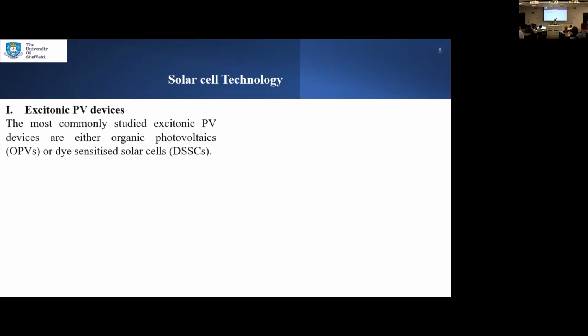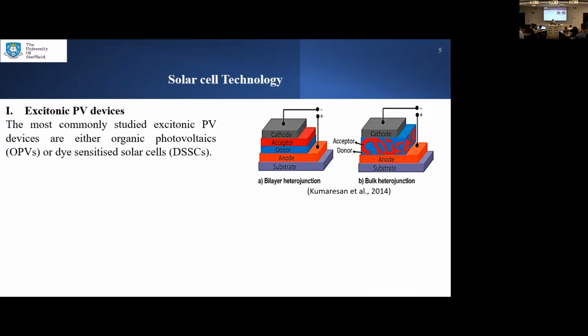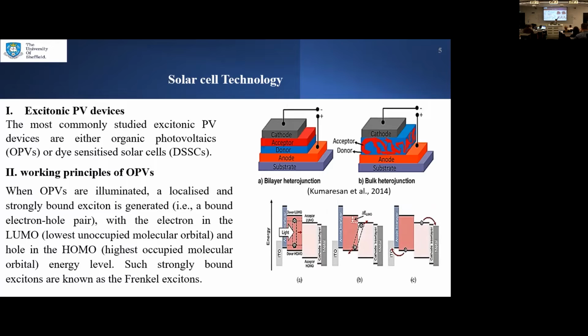Well, for organic materials, they were actually made of excitonic materials. That means the organic photovoltaic is made of excitonic materials, which means the electrons in them are being combined together. That is, you have your electrons and hole being attached together, which could be explained from here. You can see you have your electrons and hole together, and this requires a separate material in order to separate them. That is, to separate this exciton, you need an electron acceptor and an electron donor.